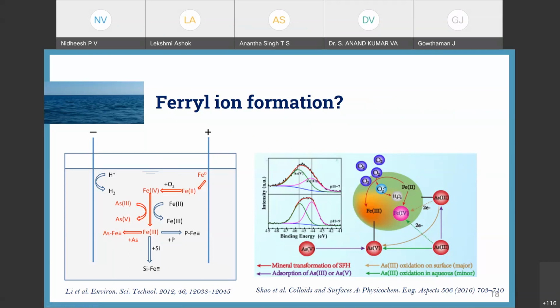That means superoxides, then hydrogen peroxide is forming, then it is converting into Fe4+. That means from the electrode, the Fe2+ is formed, then that will convert to this FeOH+, that means flocs. Then because of this H2O2 production, it will oxidize to Fe4+. Fe4+ has a good oxidation capacity, around 1.8 electron volt, in that range. So that can oxidize this arsenic 3+ to 5+, but oxygen cannot oxidize this arsenic 3+ to 5+, because the oxidation potential of oxygen is very less.